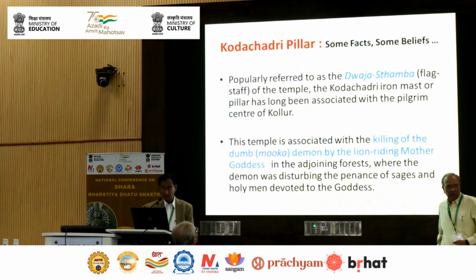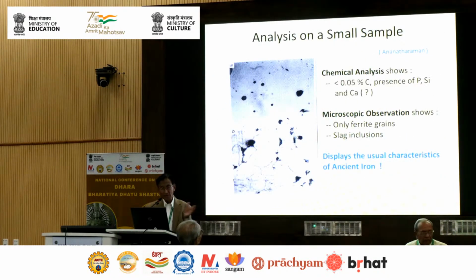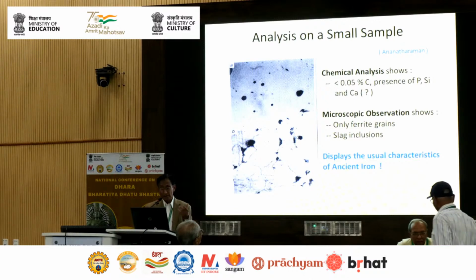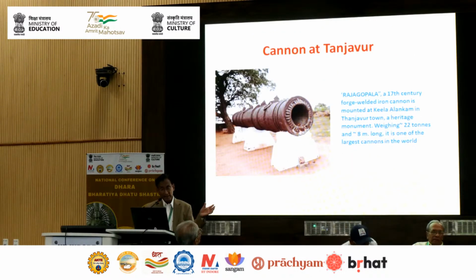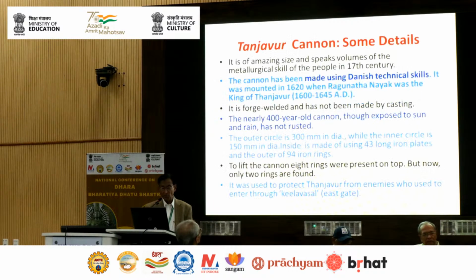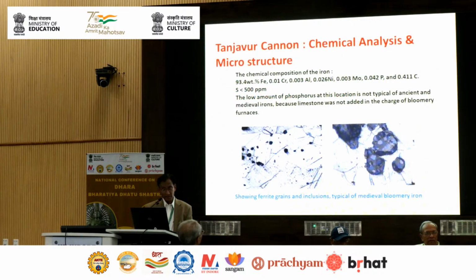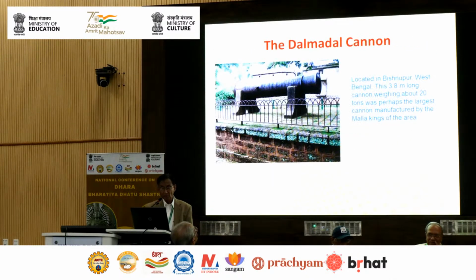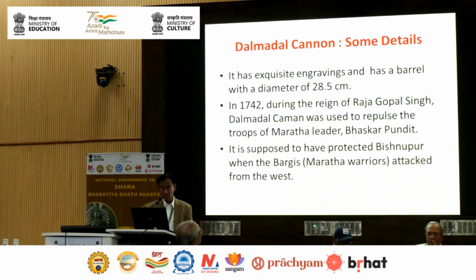And the Kodachadri. What I wanted to tell you is the analysis of these small samples. Basically you will find the slag inclusions are all there. And the cannons: this cannon in Thanjavur is supposed to be the heaviest cannon in India, probably Asia, they said, 8 meters long, 22 tons. So, the Thanjavur cannon, some details. And the composition here is much cleaner actually, because the process is slightly different. I am not getting into that. Corrosion behavior. And the Dalmadal cannon, this is in West Bengal, also pretty big, 3.8 and 20 tons.